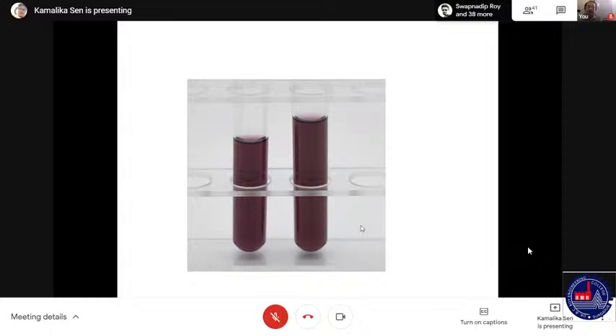So then we started doing experiments and we studied a lot of papers on gold nanoparticles. Because our gold isotope, 198 gold, had a half-life of 2.6 days, we could easily allow it to decay for 10 half-lives, that is more than 20 days, 20-25 days. Then we could go on analyzing it by TEM, UV, etc., because we would be taking it to apparatus used by others, who may have objections to introducing radioactive samples in it. So we had to wait for 25 days to decay out all of the radioactivity.